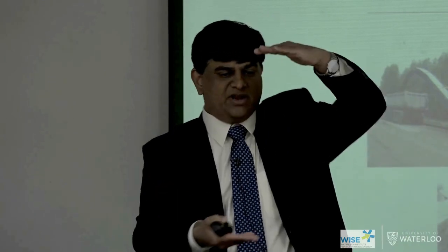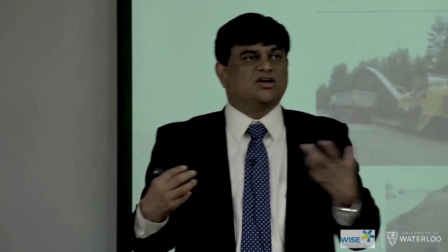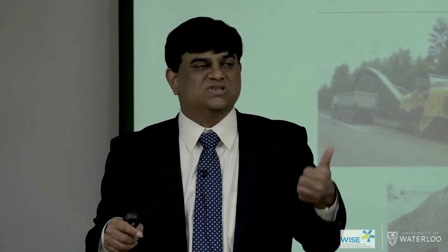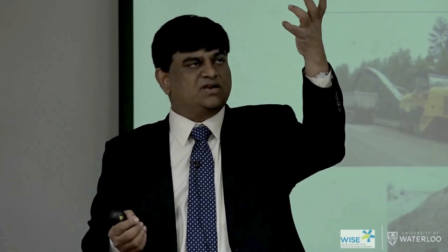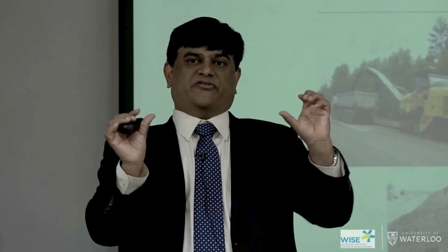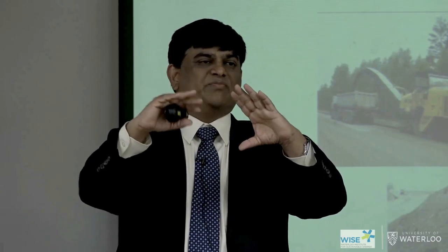What happened is the cement-treated aggregates started releasing calcium into the underlying sulfate soil, okay? Sulfate is not good, if you have soils with sulfate, it can cause a lot of problems. You have to check the sulfates in most geotechnical investigations. And the calcium coming from the top layer mixed with sulfate, it created a mineral called ettringite. That ettringite is known as a sulfate mineral. That mineral started heaving. So this whole base material started cracking, okay? So the untreated soil started heaving, and it started heaving because the calcium came from the base material, mixed with sulfate and started reacting and forming ettringite.